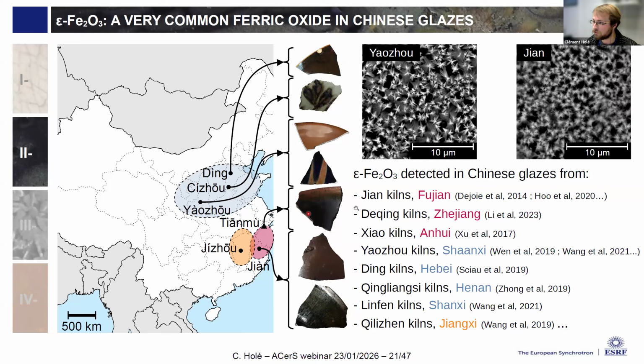And if we look at the literature, you can see that epsilon was found actually everywhere, in every site that actually produced brown glazes. And here I limited myself to the papers that were investigating kilns active during the Song Dynasty. But I have to note that there are a few Tang productions, so earlier production, that still have a few iron epsilon crystals, and that these ceramics were also copied during later dynasties, like in the Qing dynasty, and we find also this epsilon. So for being so hard to synthesize, it's actually very, very ubiquitous.